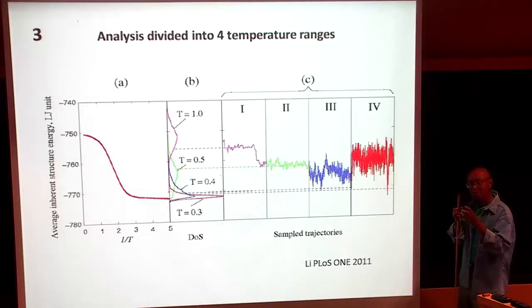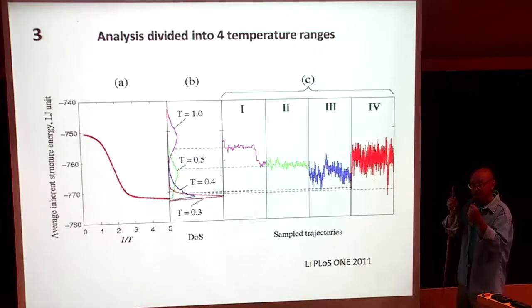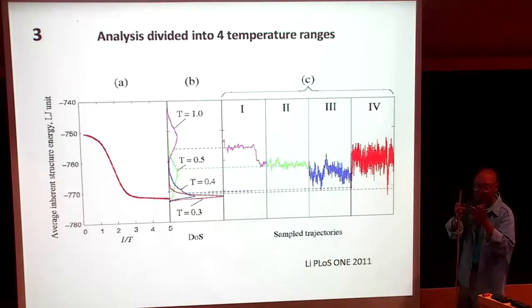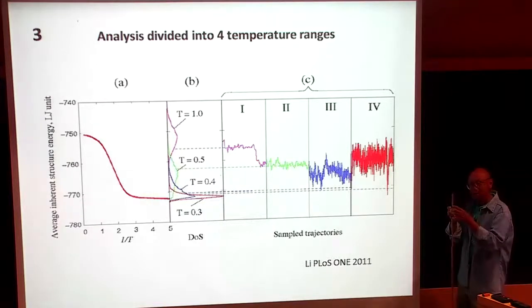So there is enough sensitivity in the details to tell you that there is some kind of a general distinction between how strong glasses behave. Strong glasses behave like network glasses. When you have a network and you want to move things, you basically have to do swapping. You have to break the bond, reform the bond. Bond exchange. People in silicon, open structure, just know all about that. Whereas in the fragile glasses, like molecular glasses, it's chains.